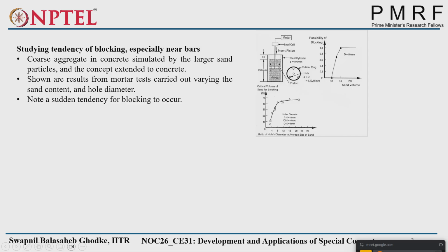So there is a possibility of blocking, and this is the sand volume. If you see a particle diameter of 10 mm, 44% sand is the critical value. Beyond that, continuous blocking is observed. Similarly, for different diameters, the plot gives the critical volume of sand for blocking and the ratio of the hole's diameter to the average size of sand. So to find out the amount of sand or size of the sand or aggregate, this type of test has been carried out.